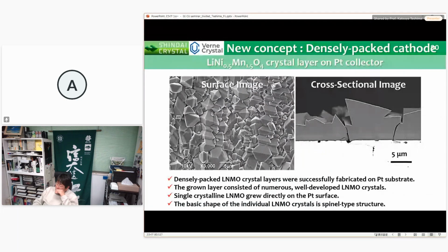Next is our new concept material, densely packed cathode materials. These are images of LNMO crystal layers on a platinum substrate. As clearly shown, densely packed LNMO crystal layers were successfully fabricated on the platinum substrate. The grown layer consists of numerous well-developed LNMO crystals. Single crystalline LNMO grew directly on the platinum surfaces, and the basic shape of the individual LNMO crystals is a spinel type structure.